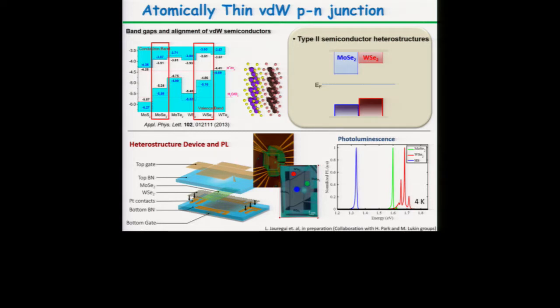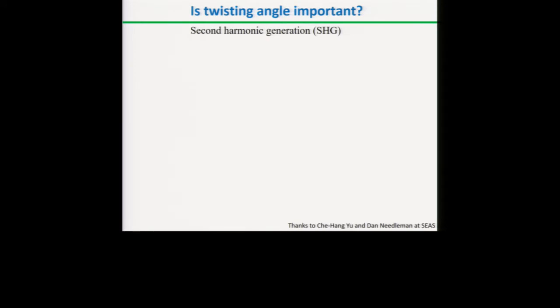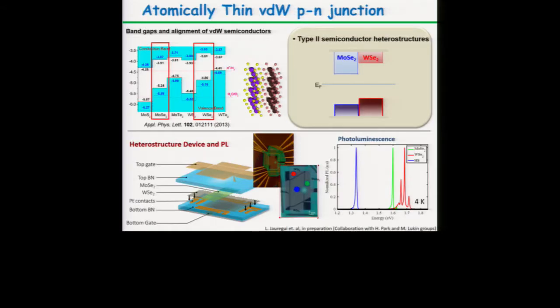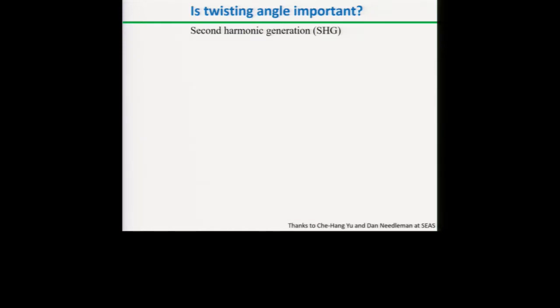It's around 1.3 electron volts. There is very low recombination from each of the individual layers. Once we obtain the photoluminescence on the heterostructure, each of the layers doesn't give much exciton emission. All right, but I want to mention here, we put these two materials together, but the alignment between them is important.